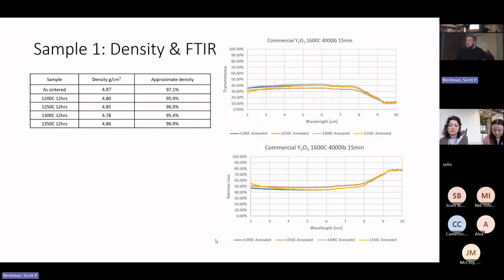After annealing at different conditions, we're able to see the different transmittance values and the different densities that we were able to achieve. We found that our as-sintered density was 97.1%, and then as we annealed, our density actually went down, which again is due to the presence of the carbon in the as-sintered pellet. As that carbon leaves, it leaves basically empty spaces or air, which of course has a lower density than our solid product.